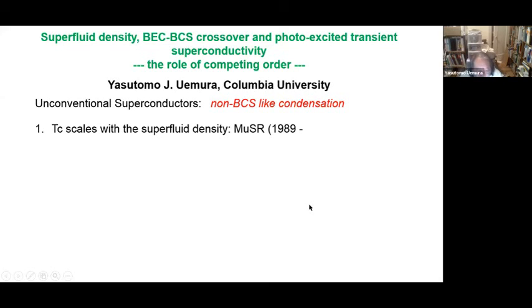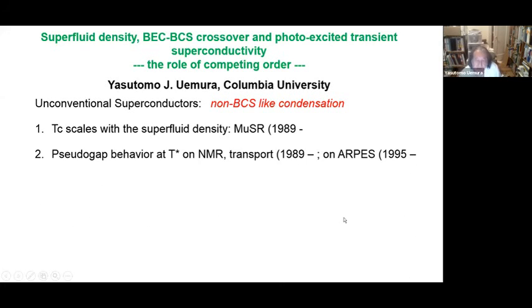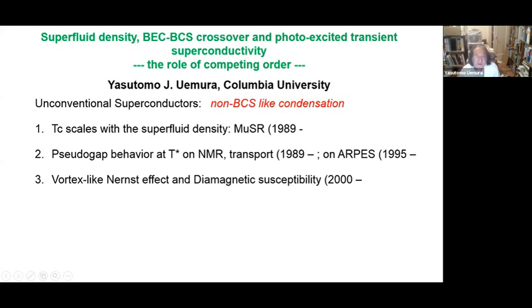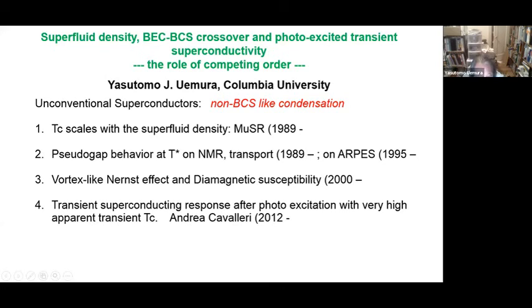So the first one is Tc scales with the superfluid density. This is something we did with MuSR since the very early days. Second is pseudogap behavior, T star, measured by NMR, transport and ARPES later. Third, a non-BCS-like feature is the vortex-like Nernst effect and diamagnetic susceptibility that was pioneered by Ong. And the fourth one is just introduced by Andrea, that he found a very nice transient superconducting-like response after photoexcitation